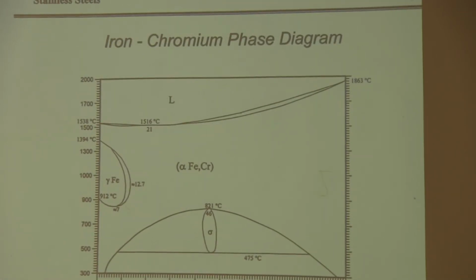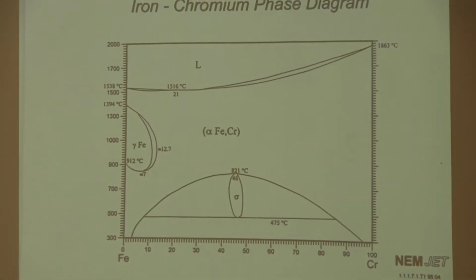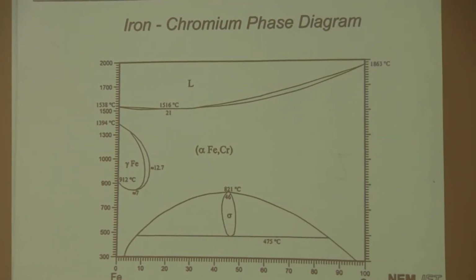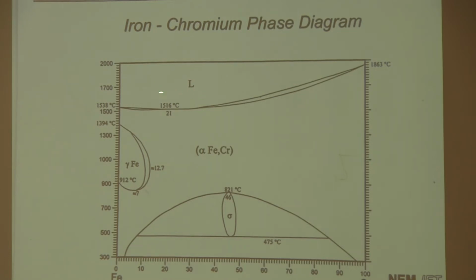So, like I said earlier, stainless steel at its very essence is an iron chromium alloy, and so what this is called is a phase diagram. I believe Professor Eager may have showed you, or Simone may have showed you, the iron carbon phase diagram. This is actually the iron chromium phase diagram, and over on this side you've got 100% iron. And over on this side you would have 100% chromium, and everywhere between, here you've got 50% chromium and the like. This axis is temperature, and so if you take a 10% chromium alloy, for example, and you come up through here, when it's liquid you're going to be up in the liquid phase. As it solidifies you're going to come down through an alpha, which is a ferrite phase, and then you're going to come right along here.